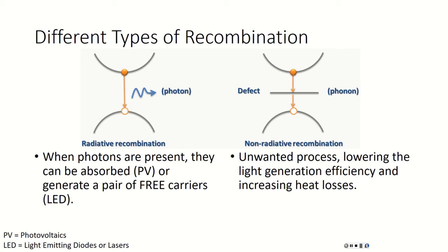Oh, so you're talking about this one? Yeah, the one that emits light will have a very high oscillator strength, because the probability is very high that it will transition from the excited state down. If you have a defect state, typically those are localized states, so the overlap is relatively small, which means your oscillator strength is low, so the probability is very low and it's not really emitting light.